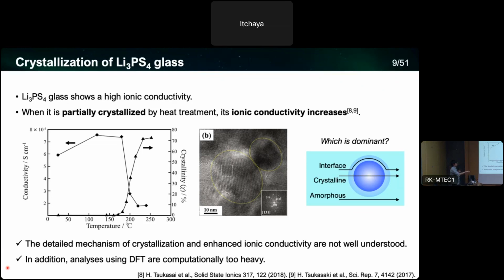This is the schematic of a partially crystallized domain surrounded by the amorphous glass domain. So one possibility is that the interface between the crystalline and amorphous plays a role in improving the conductivity, or the precipitated crystalline part is important, or the amorphous glass region changes its properties to enhance the ionic conductivity. So the understanding of these atomic scale mechanisms is not sufficient. So from our simulation side, we would like to clarify what is actually happening behind these materials.